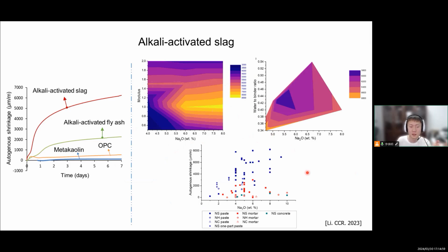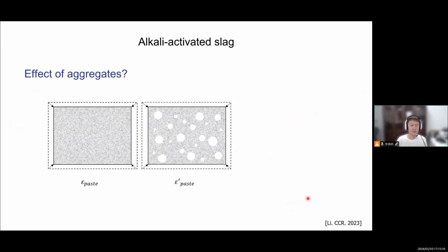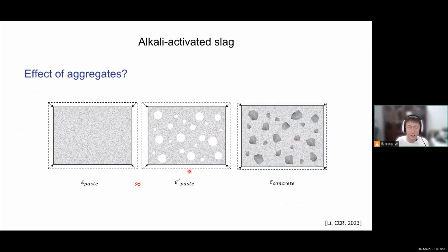Another parameter is the presence of aggregates. So compared to paste, the mortar and concrete will show lower autogenous shrinkage. So people will think that, of course, there will be aggregates, so you have less material to shrink. Of course, the shrinkage will become smaller, but I want to emphasize that actually that is not true. The reason for the lower shrinkage of concrete is not just a dilution effect. For example, if we consider these two systems, one is the pure paste, one is paste, but we take a part of the paste out instead of hollows. So we can see that there will be less paste there, but the shrinkage of these two systems is actually similar if we do not consider the local geometry. Then the reason why the aggregate can restrain the shrinkage is because aggregate is stiffer than cement, and also it doesn't shrink itself, so that it can restrain the shrinkage. It's not just because there is less cement or less paste to shrink.